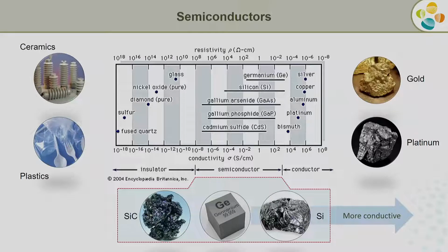What is important about these semiconductors is that we can tune the chemistry. So in the case of silicon, we can dope it with foreign atoms, boron, for instance, and make it highly conductive. Or introduce other elements like oxygen and oxidize silicon and create silicon dioxide, one of the best dielectrics. So essentially, by chemical modification, we can span the electrical properties across the entire range we see there. And this is what makes silicon the magic material, a material that comes with all these interesting characteristics, and which is the reason why it dominated the area of microelectronics.